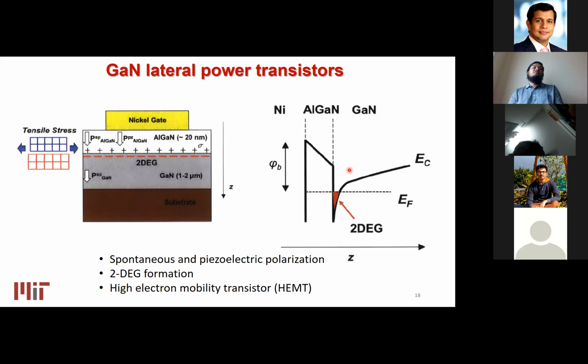This is very unique for this material system, because in any other material, if you want to form a channel, we either have to dope or apply a voltage to invert the semiconductor itself. But because of this unique crystal structure, when we grow this gallium nitride heterostructure, it forms a channel by definition, with high carrier density and very high mobility. It's a very attractive option for high frequency and high power electronics. The transistor built using this structure is called a high electron mobility transistor, or HEMT.